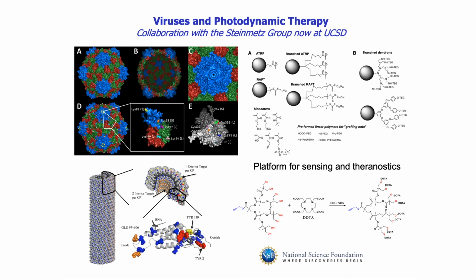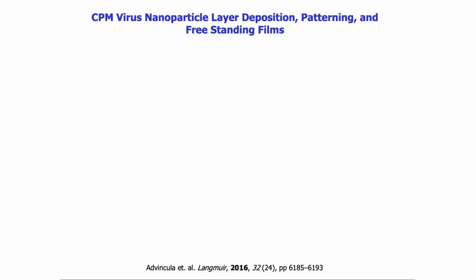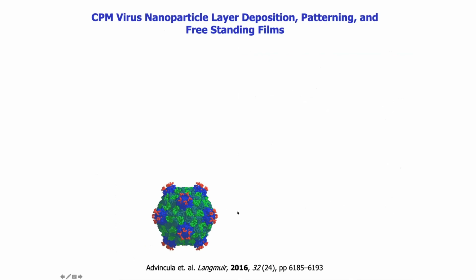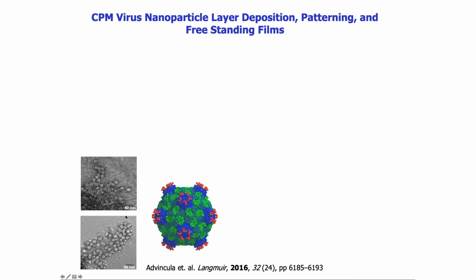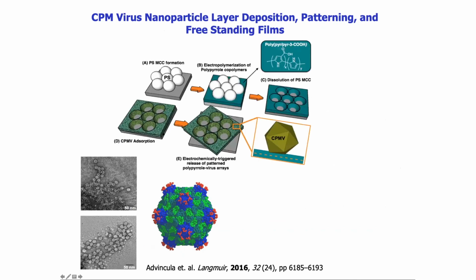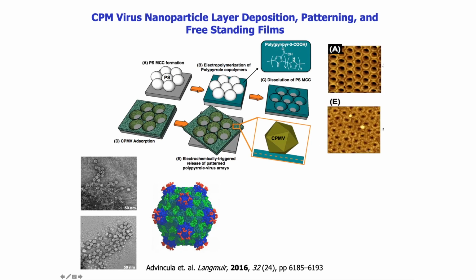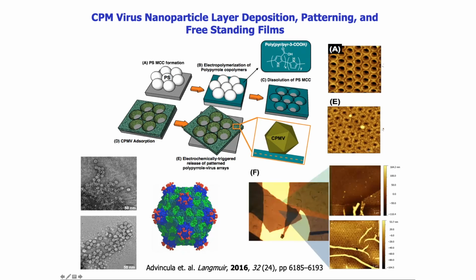But I won't focus on the work with the phototherapy, but rather show you that we can take those viruses like this and then pattern them on colloids. So these are the TEM images of the viruses, and then we pattern them on colloids similar to what we did before. In this case, the viruses are going to deposit on the ring structures or the arrays that are shown here, and then we were able to remove them in terms of their grafting structure. And so here are the templates, and here are the viruses surrounding these templates, and we were able to remove them as freestanding films out of the original substrate.